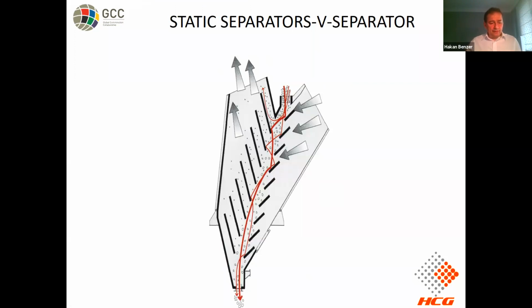This is a typical static type separator which was developed to be used in combination with high pressure grinding rolls. As I said, a cake is formed by the high pressure grinding rolls, and that cake should be deagglomerated before separation, and the deagglomeration occurs here. So this V separator is designed both for deagglomeration and for classification, and the fine material can be sucked out by a fan filter at that point, and the coarser part which settles down can be circulated back onto the equipment. The feed is directed down through baffles to meet the rising airflow. The compacts are broken as they collide with the baffles here.